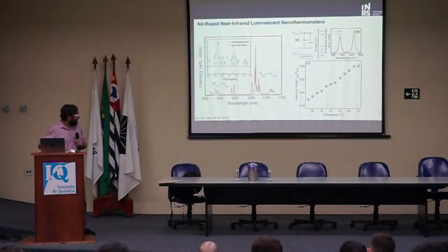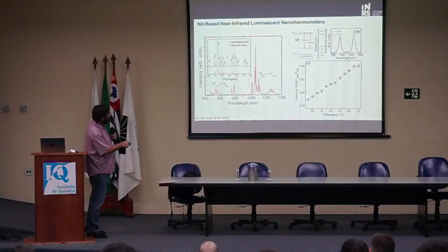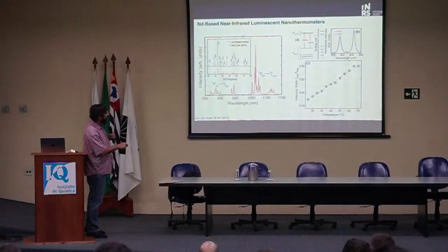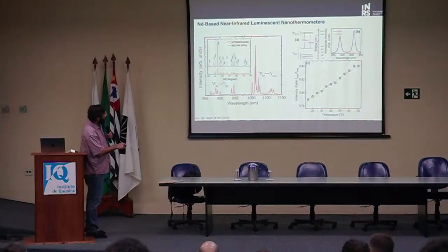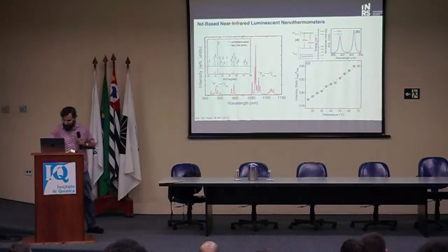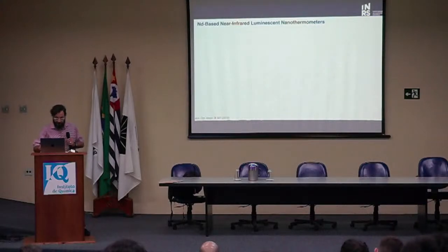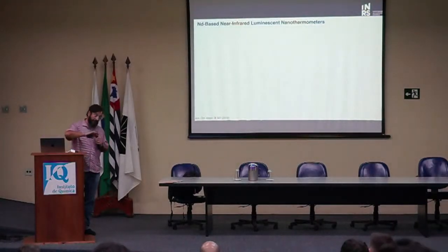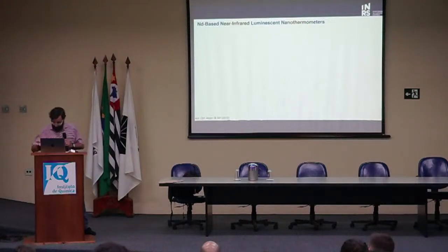Yes. So again, neodymium. I didn't mention that the thermometry with neodymium occurs in a slightly different manner. It's still ratiometric, but within the same excited state, with their Stark states. So the excited states split further, and these, what we call Stark states, are actually Boltzmann coupled. So we can again calibrate and then determine temperature. So this is in the first biological window, and I'll show you the results. But we've also since worked in the second biological window, we've done thermometry, and in the third biological window as well. So we've covered all the windows when it comes to thermometry.